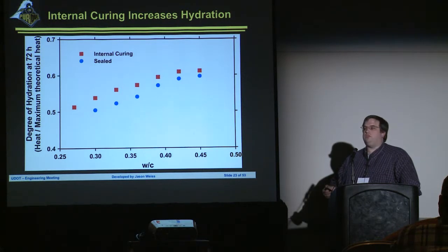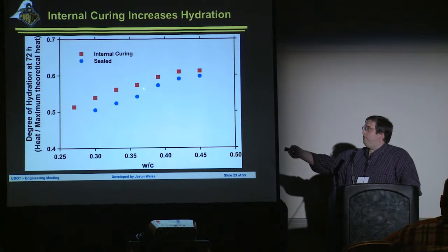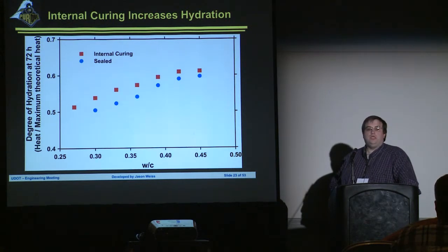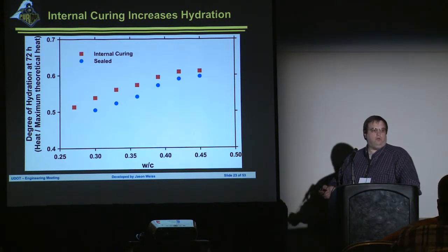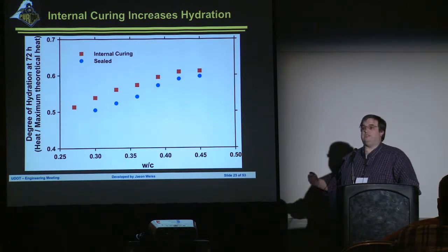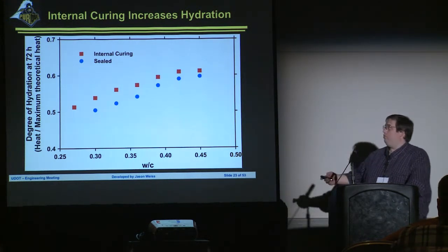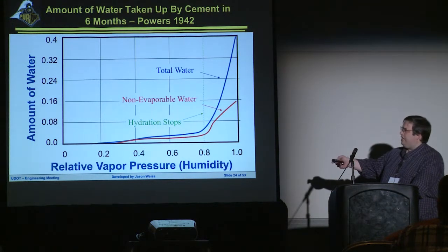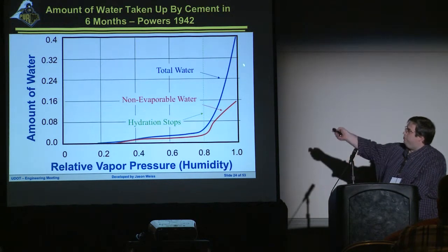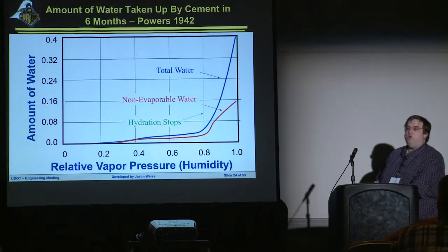So the benefits of internal curing are you're going to get more reaction inside of the system. This is important for Portland cement. It becomes even more important when you've got supplementary materials. You're using slags, you're using fly ash, you're using silica fume. Even more and more important. Right? Again, we saw this before. Keeping the humidity high allows more reaction to take place inside of the system.